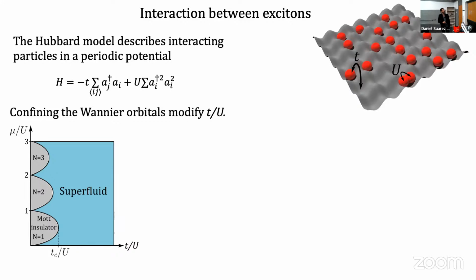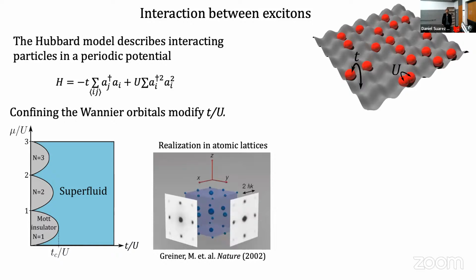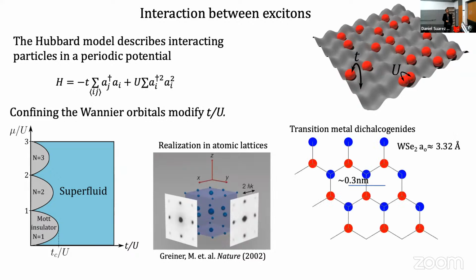One way to do it is by confining the Wannier orbitals of the particles in the system, so making them more confined. And this was achieved several years ago in atomic arrays. But more recently, the very celebrated result was achieved in a transition metal dichalcogenide system, in particular in a bilayer.